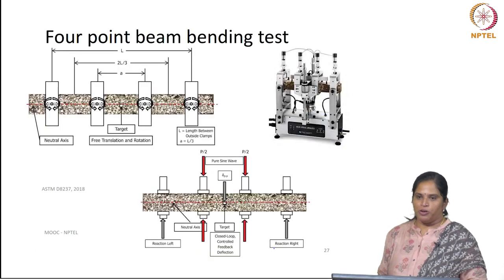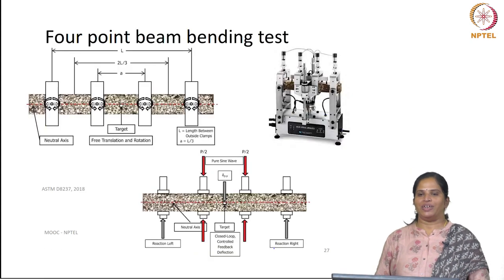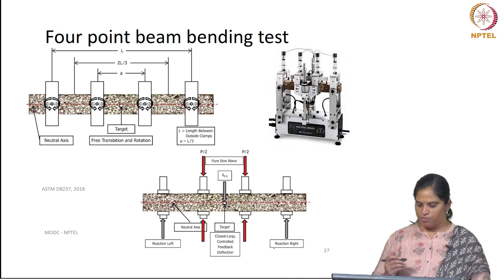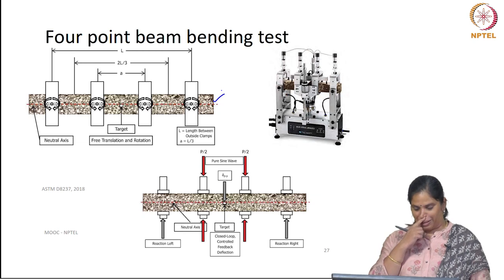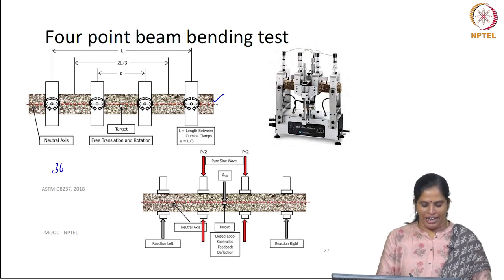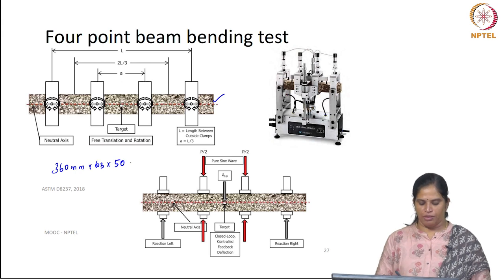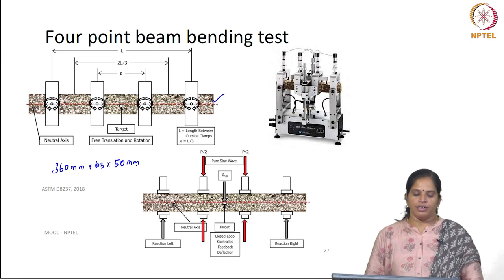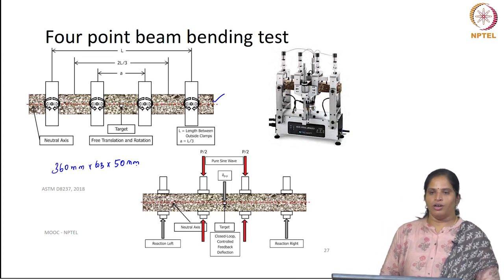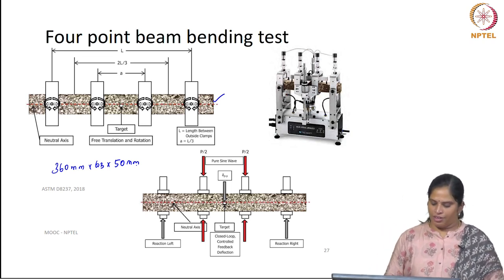So, a 4-point beam bending test. We test a slender bituminous mixture beam as shown here in the figure. The beam is of size length 360 mm, width 63 mm, and depth maybe 50 mm. So this slender bituminous beam is subjected to loading as shown here in this picture in a 4-point